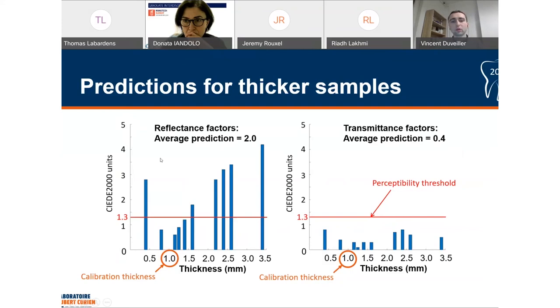And you can see that the prediction accuracy forms a kind of envelope that is centered on the calibration thickness. So only the samples with thickness close to the thickness of the calibration sample are accurately predicted. This means that our model is not stable with respect to the thickness, at least for the reflectance factors. Because for the transmittance factors, all spectra were predicted below the perceptibility threshold. So this last result is a good one, a satisfying one.